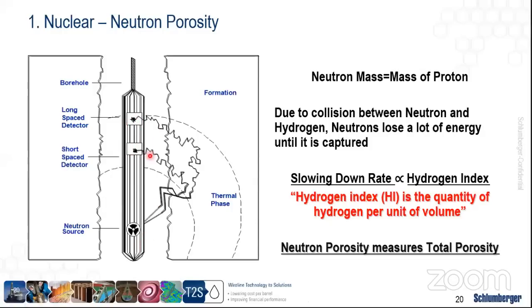The reason why we have two detectors and we're not only relying on one detector is that the near detector is primarily attenuated or affected by the borehole condition, such as washouts or hole rugosity, as well as the borehole fluid. But if we have another detector that's farther from the source itself, then it reads deeper inside the formation, and it's less affected by the borehole condition, and it's actually seeing what is there inside the formation. Using these two different measurements from these two different sensors, we're trying to correct for any borehole effect that might be affecting the final output of the neutron porosity.